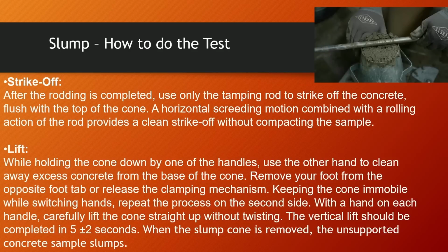All right, strike off. So like we said, you need to put a little bit of extra on top. After the rodding is completed, you use the tamping rod and you strike the concrete off flush with the cone. A horizontal screeding motion combined with the rolling action of the rod gives you a clean strike off surface without compacting the sample. The lift is important. While lifting that cone off while holding the cone down by one of the handles, you use the other hand to clean away the excess concrete from the base of the cone. You remove your foot from the opposite foot tab or release the clamping